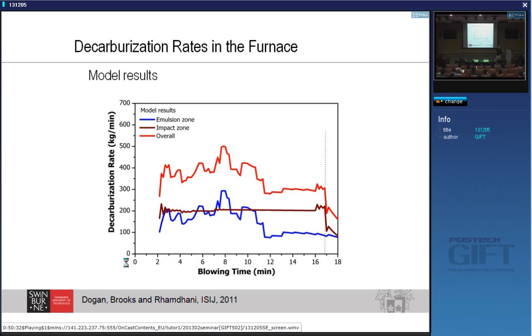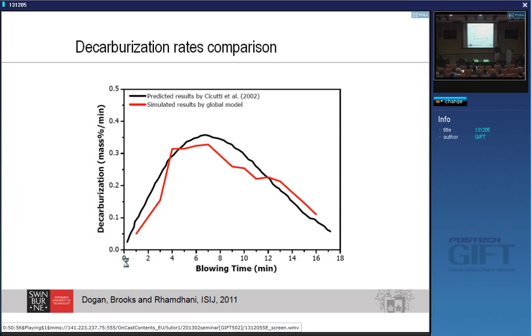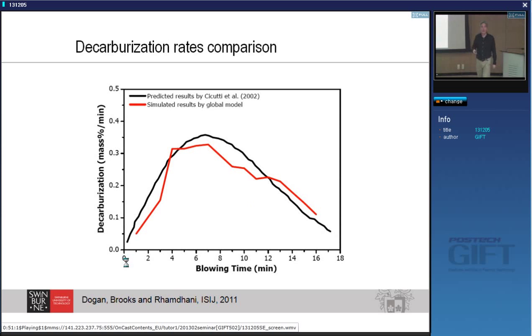on. And what we see here is that early on, the decarburization of the emulsion gets high, and then it dies off as the droplets become dense. Then in the impact area, it stays relatively constant, and this provides this curve. Now, when we combine all these calculations together and we compare it to plant data, we get curves like this. So this is the result from the plant, and this is the result from our model.